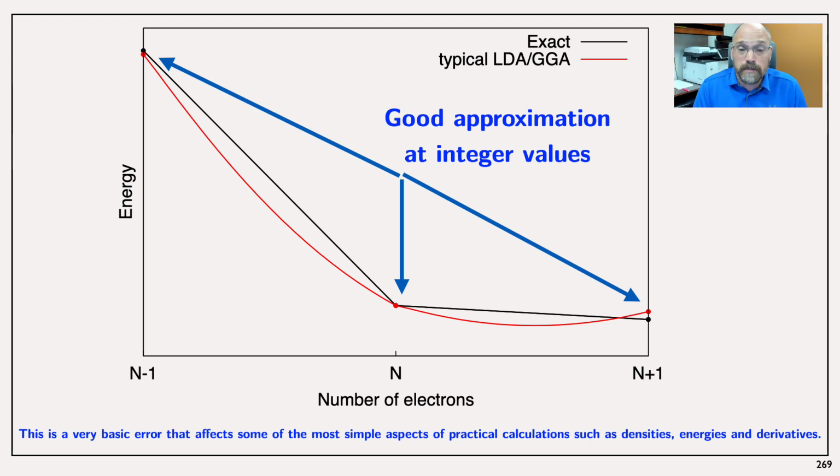So basically that means they are not continuous. And that discontinuity is actually part of the band gap. Now, if you look at LDA and GGA, the derivative on the left and on the right of the red dot is the same. The function is continuous and the derivative is continuous. Therefore, you are missing out this discontinuity in the derivative.